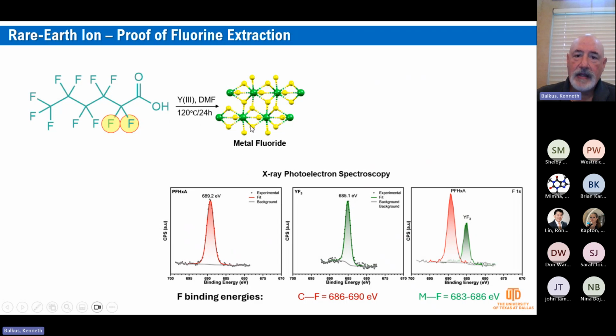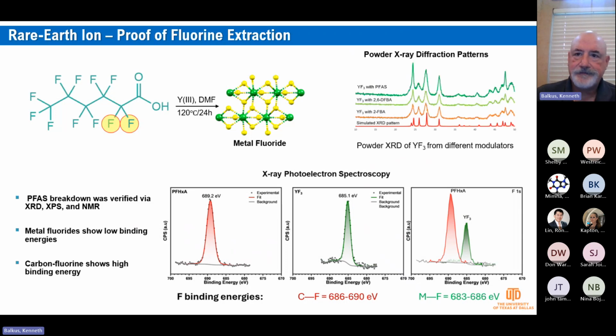But at any rate, we make the metal fluoride, and by XPS, you can show that you readily make the metal fluoride. And if you want to just compare it to the starting perfluorohexanoic acid, you can easily tell the difference between the organofluorine compound and the metal fluoride. So we know that chemistry works very well. And of course, you can also verify that by X-ray diffraction too, in addition to the XPS.